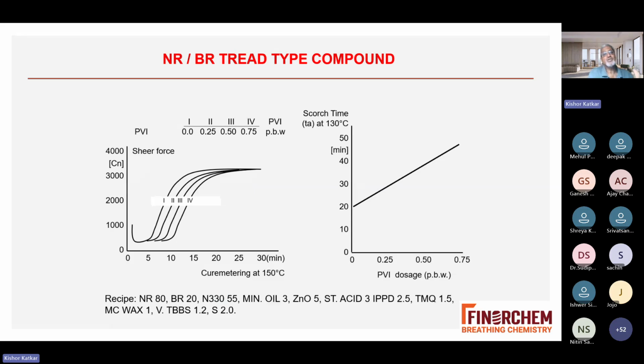Now you can understand, as you increase the dosage, this is a graph of curing time versus the modulus. As you increase the dosage from 0 to 0.75, your scorch safety is proportionately increasing. Here you can see. However, you have to understand, when the scorch safety is increasing, proportionately your cure time will also increase. Then what are the options? Instead, use sulphenamide wherever possible, or change from CBS to TBBS to MBS, and your scorch stability will increase. However, your cure time will come down. So this is the difference between the retarder and the sulphenamide. You can judge depending upon your requirement and the configuration of the product.